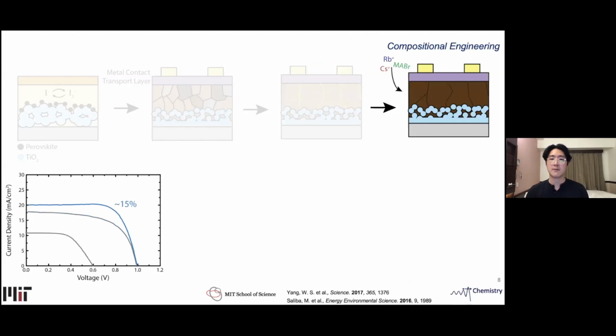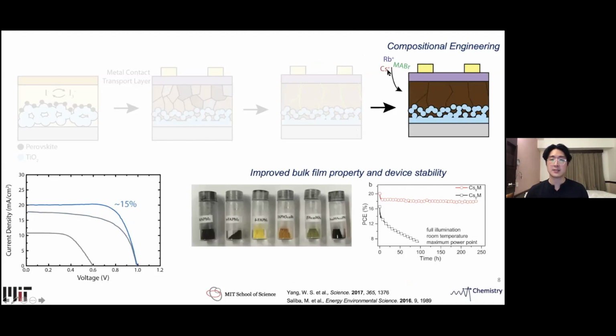Currently, a lot of effort has gone into composition engineering, where a small amount of additives such as metal cations or various compositions is added into the perovskite bulk to improve its bulk film property and device stability. On the right, I'm showing efficiency tracking over a long period of time. With the addition of a small amount of cesium cation, there is improvement in the stability, as shown by the maintaining of its efficiency. This resulted in efficiency of around 20%.